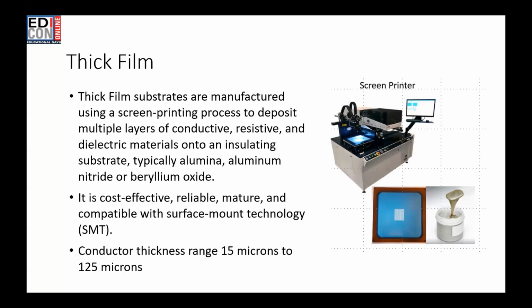Thick film substrates are manufactured using a screen printing process where we deposit multiple layers of conductive, resistive, and dielectric materials onto a dielectric substrate. That would be alumina, aluminum nitride, or beryllium oxide. It could be other materials as well. It is a very cost-effective, reliable, mature technology, and compatible with surface mount equipment. In terms of the thicknesses, the popular range is between 15 microns and 125 microns.